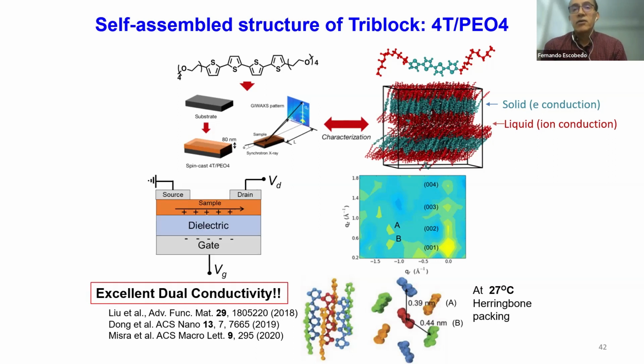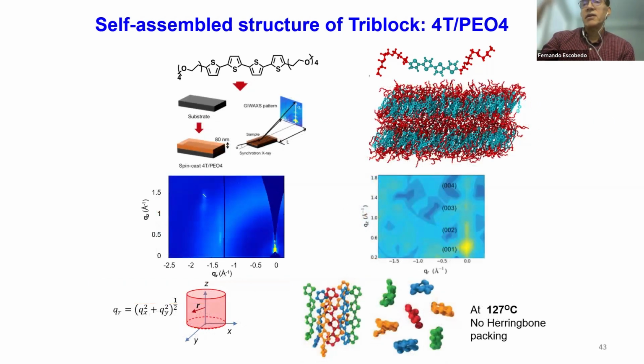And when our collaborators characterized the system by this sort of electrical test to see ionic conductivity and electron conductivity, they found that it was an excellent dual conductor. In fact, comparable or even better than the best one that has been reported in the literature. So we felt that, wow, we were at a very, very promising start by having chosen that initial chemistry, but of course we wanted to go beyond that and potentially optimize this. So this is just to show you that there's a temperature range of operation. If you go too high, then the system is going to melt, and then you no longer have this sort of herringbone structure for the thiophene rings.